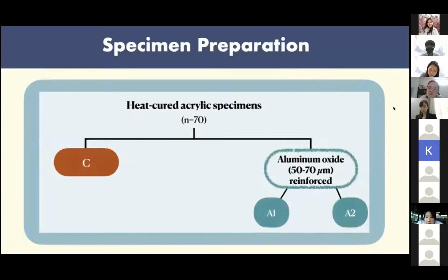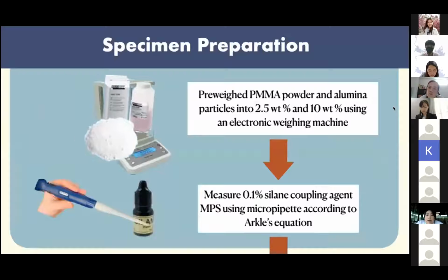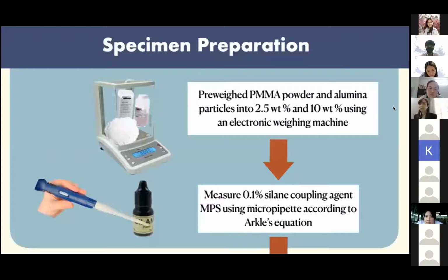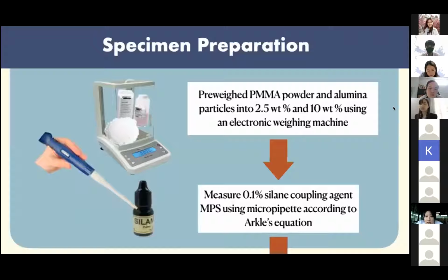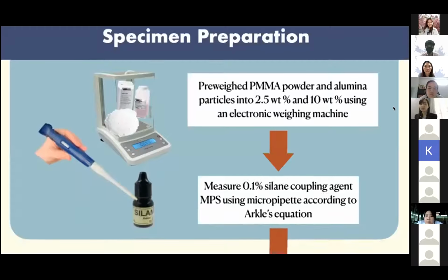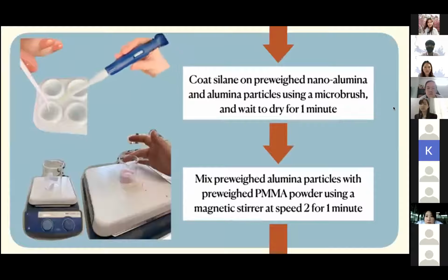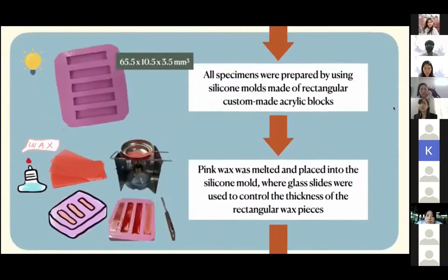The abbreviations for the 3 experimental and control groups are as shown. Firstly, PMMA powder and alumina particles were pre-weighed into 2.5 and 10% by weight using an electronic weighing machine. Then silane coupling agent MPS was measured using a micropipette according to the equation. Silane was then used to coat the pre-weighed alumina particles using a microbrush and left to dry for 1 minute. Then the pre-weighed aluminum oxide particles were mixed with resin polymer powder using a magnetic stirrer.